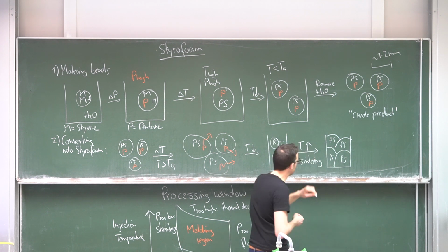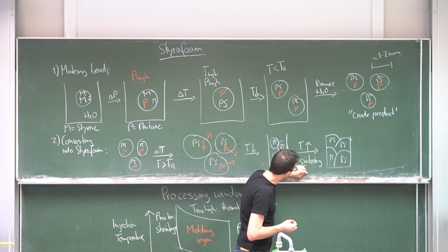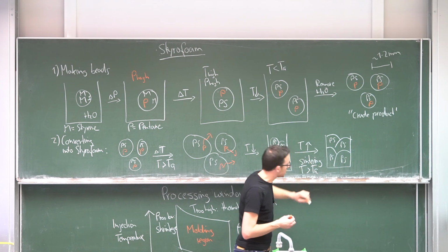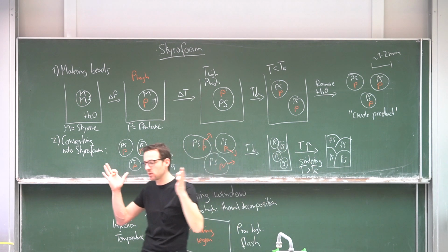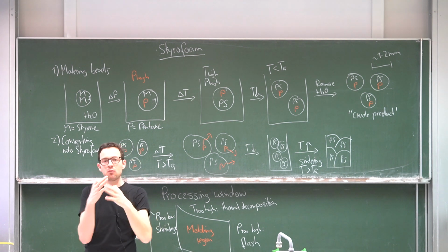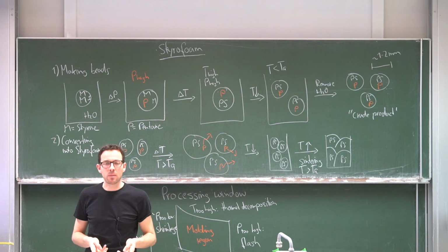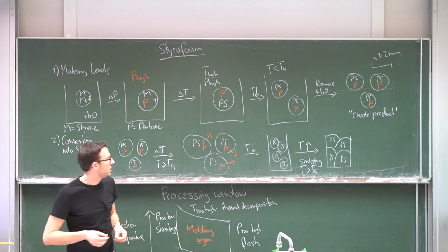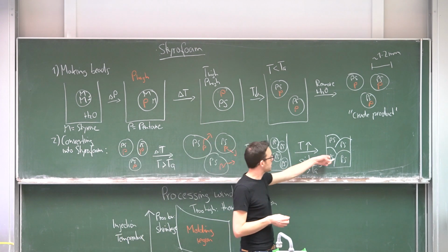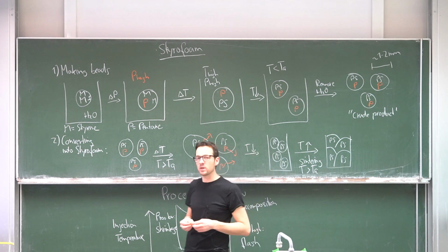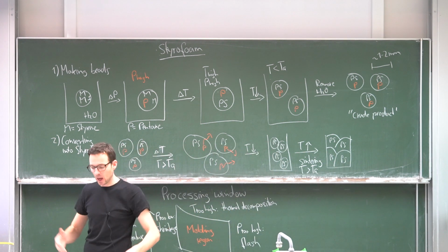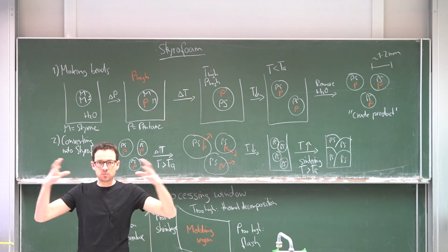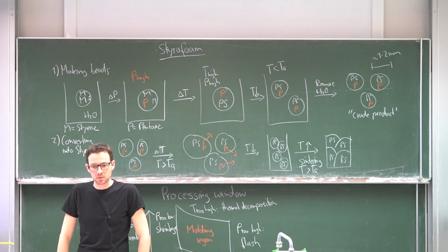Sinter or we fuse them, and we do this again using a temperature that is larger than Tg or roundabout Tg to make sure that these polymer beads become sticky without completely melting or becoming liquefied into a solid material. And if we do this, the beads fuse and we have our polystyrene or styrofoam made out of fused expanded polystyrene beads.